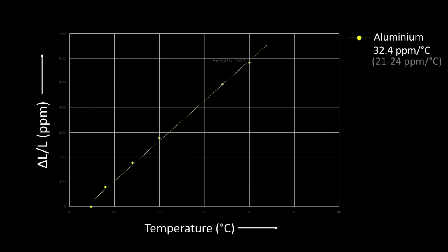We'll start with aluminum. The individual measurements show a fairly linear relationship between length and temperature, which I guess is a good sign. If we measure the slope of the graph, we find a value of 32.4 ppm per degree Celsius, which frankly is quite a bit too high given the generally accepted range for aluminum. So this indicates that our setup may not be very accurate. But before we conclude this, let's take a look at some of the other values.